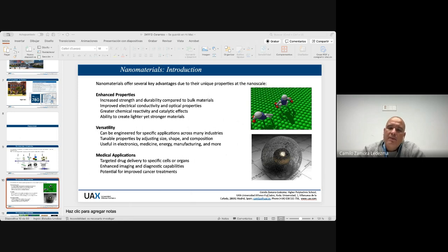For instance, as I mentioned before, key parameters like the nanocarbon allotrope dispersion play a crucial role in the final performance of the materials. The presence or absence of alumina seed also plays a crucial role. The boehmite at the beginning, the size of the boehmite grains before the annealing, is also important. And for the SPS, as I mentioned, the temperature, the annealing time or the temperature ramp will play a crucial role during the preparation.